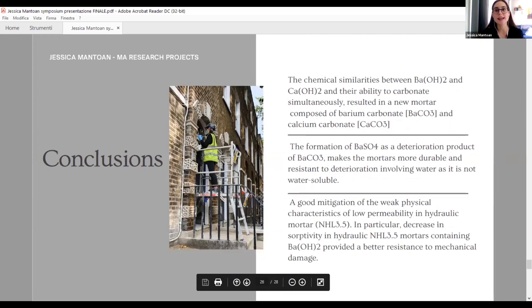In conclusion, I can say that I confirm that the chemical compatibilities and similarities between barium hydroxide and calcium hydroxide make the creation of barium hydroxide mortar possible. And the most important achievement is that the formation of barium sulfate in mortar containing barium hydroxide is extremely positive, because it allowed a better resistance to any water sulfur decay mechanism. So in this case, the formation of salt and acid rain.